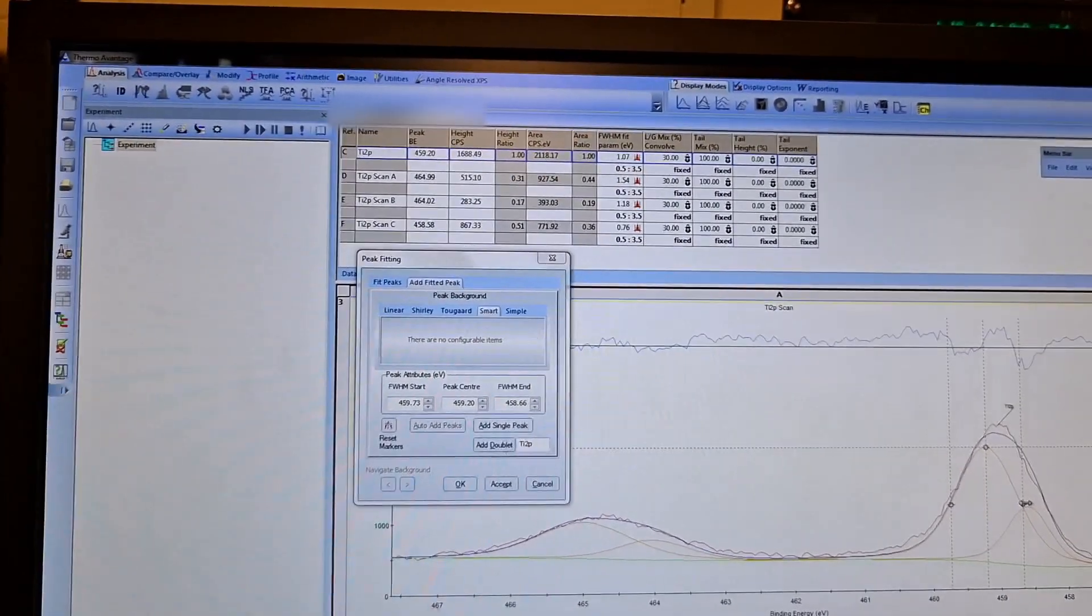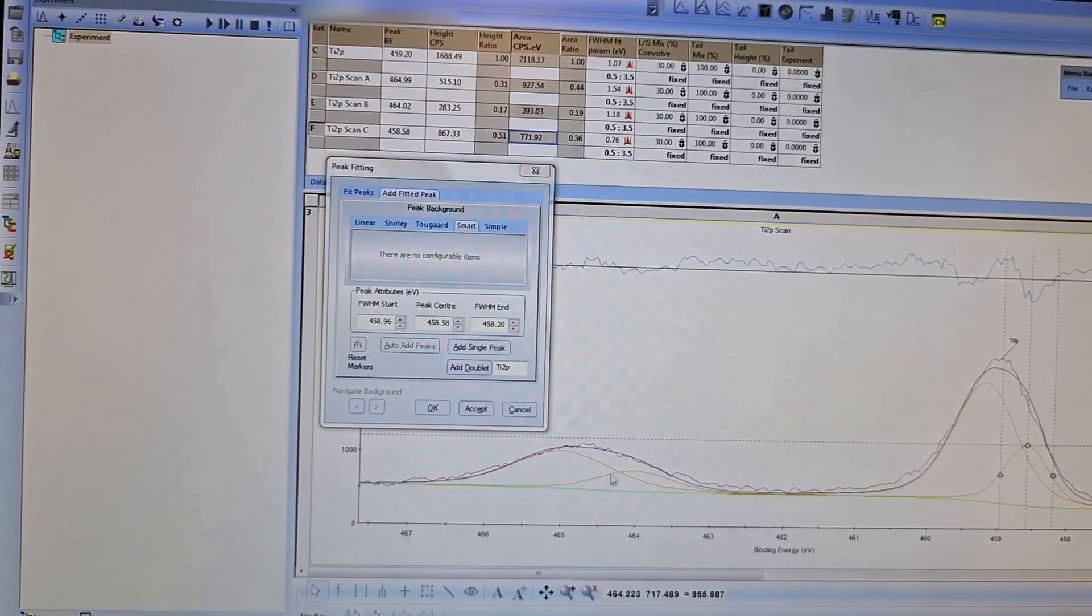This red one here is the real signal, so it seems a little bit off. I want to make this fit just by using my view. The reason is that if I try to fit it, it becomes horrible. I can check the area. For instance, you can see the area. Titanium 2p, which is this big peak, area is right now 770, and this small peak should be around less than 400. It is good right now. Areas match with each other.